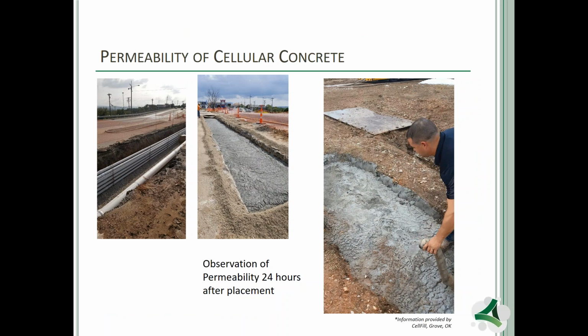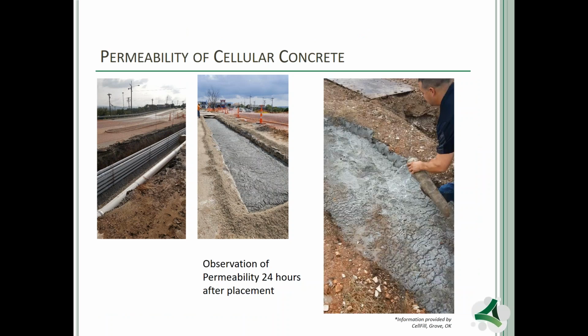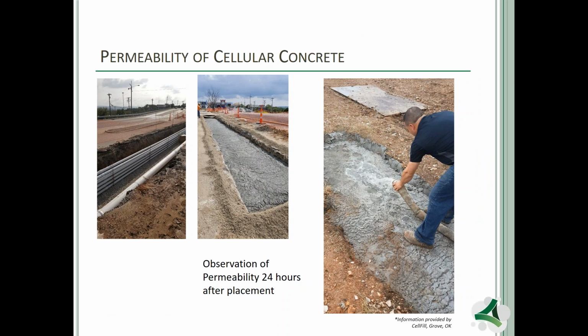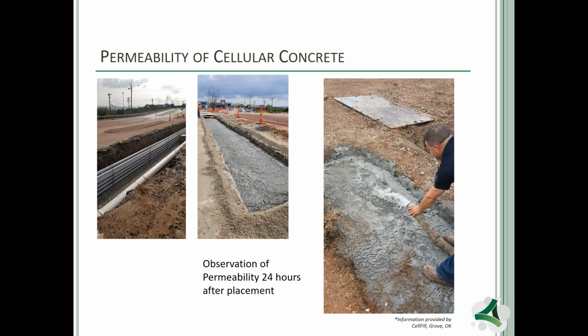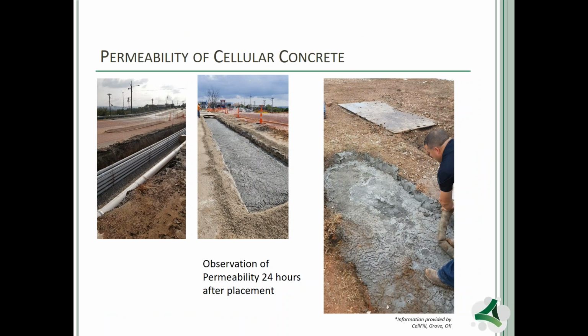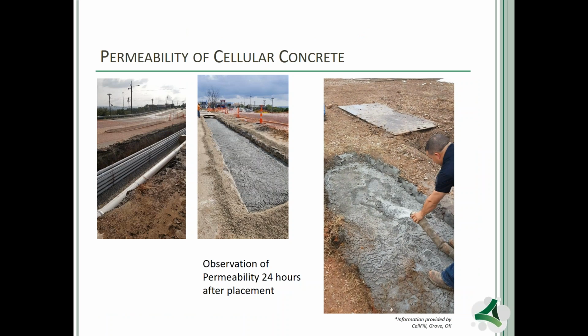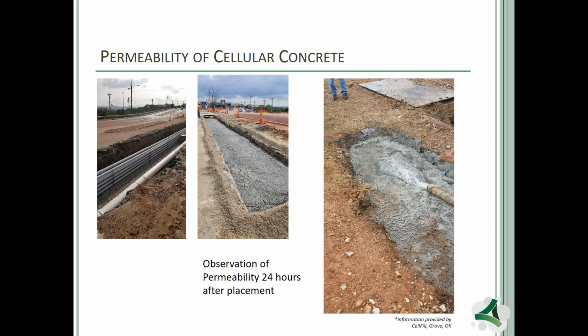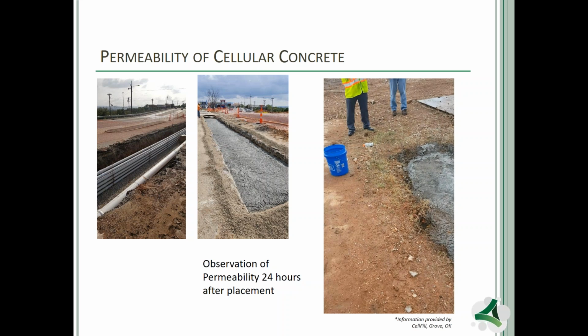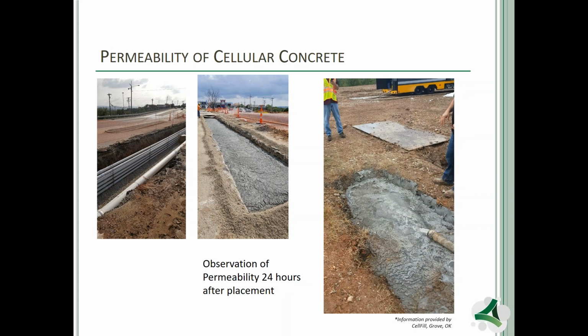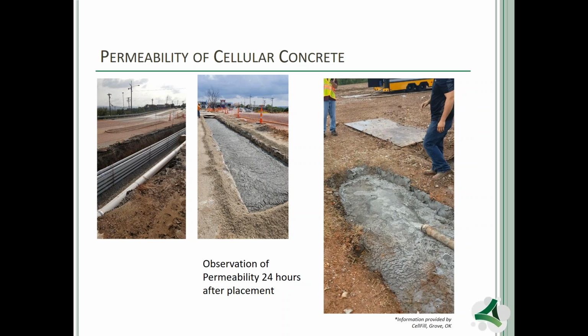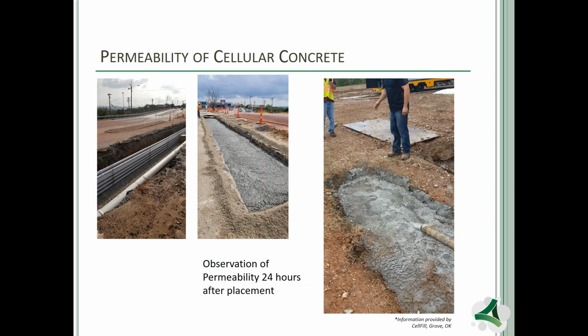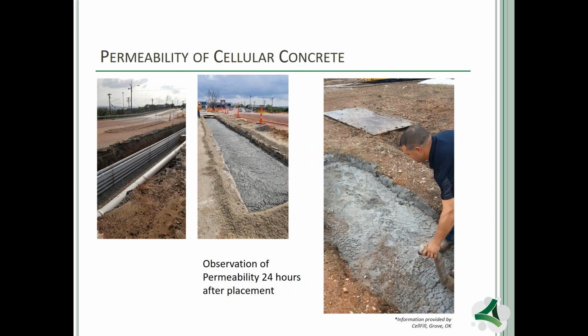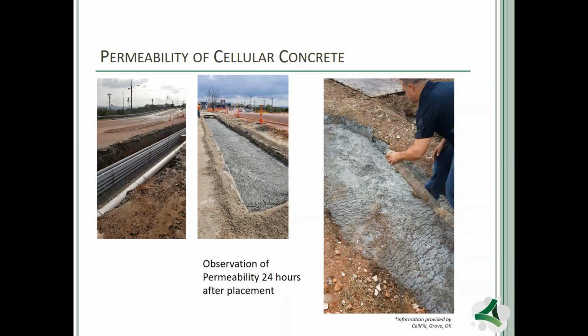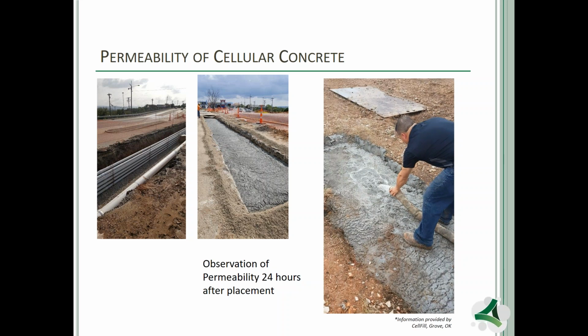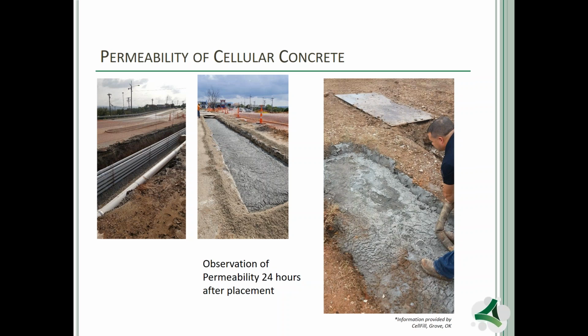The Missouri DOT wanted to have a live demonstration of the permeability of cellular concrete, and they asked an installer to dig a 4 foot deep test trench, fill it up with pervious cellular concrete, and they did that one afternoon. And the following morning, the Missouri DOT came out for a demonstration on permeability. And this was the demonstration that was observed for the Missouri DOT on the test trench.